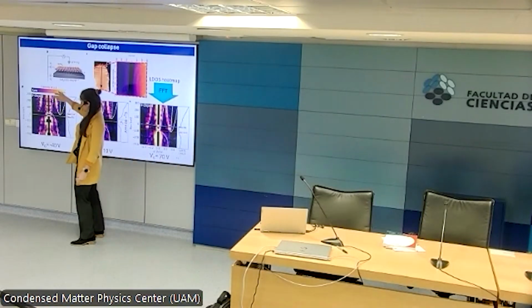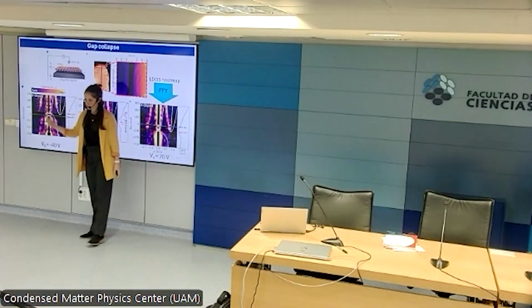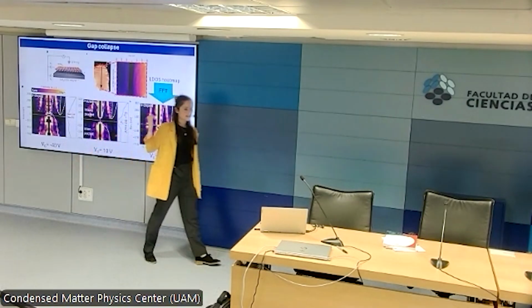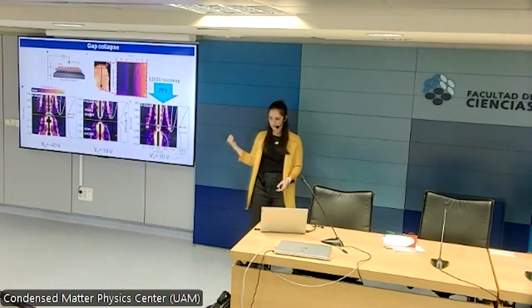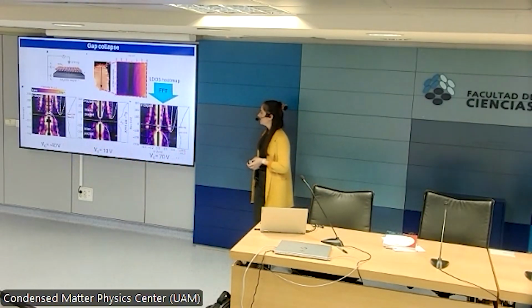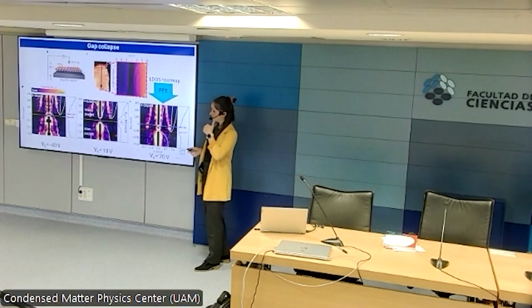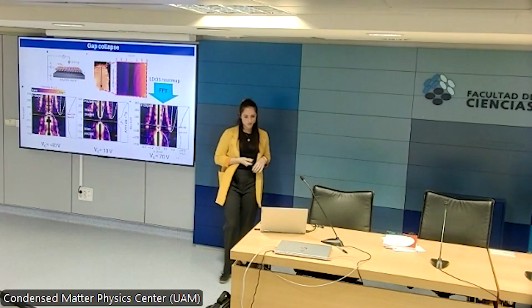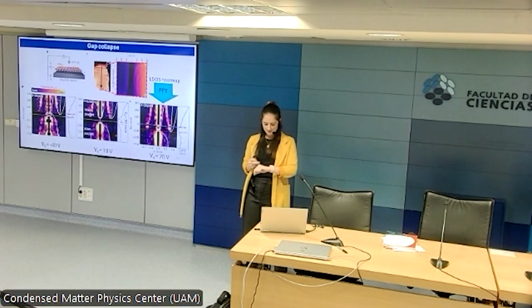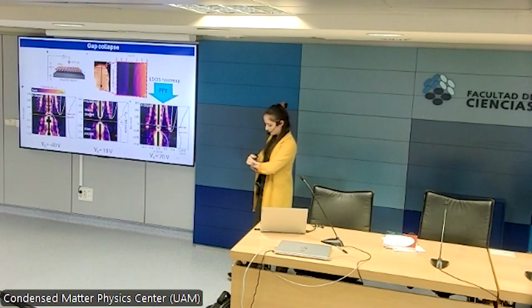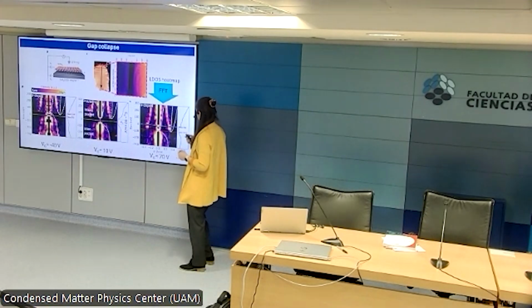The opposite, but in the other direction of the Fermi level, happens for negative bias. So this tells us that we can collapse the band gap of the excitonic insulator. So it is indeed an excitonic insulator. So check.